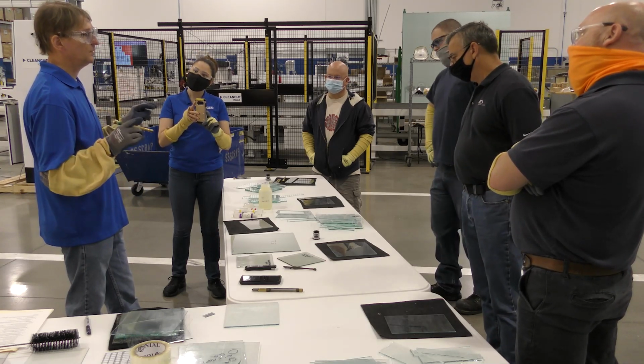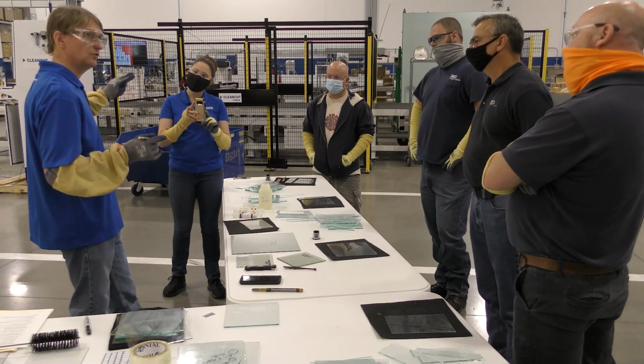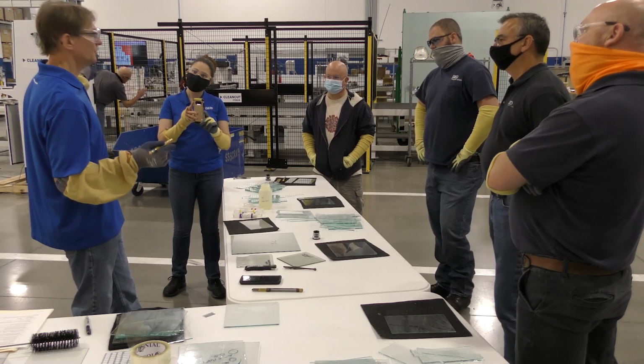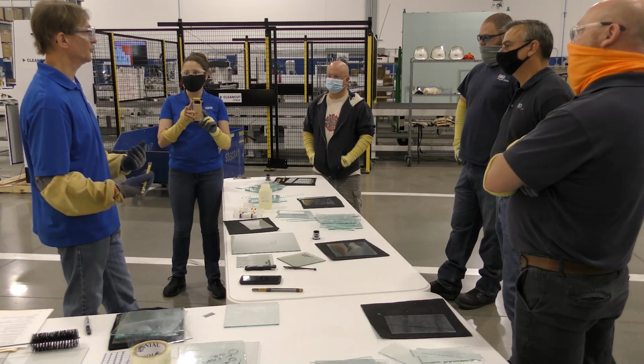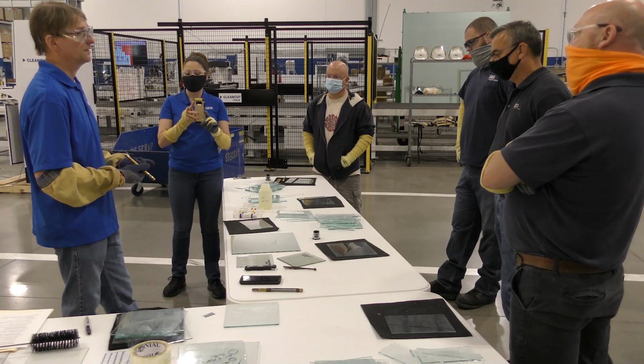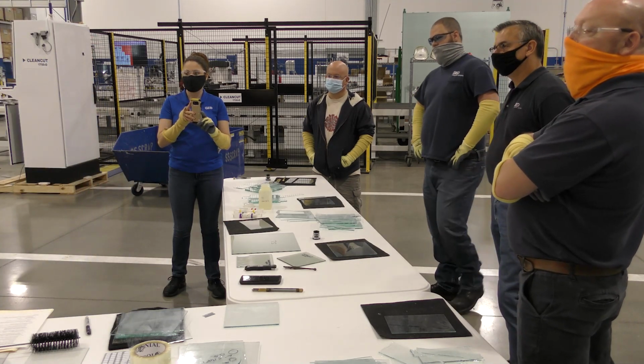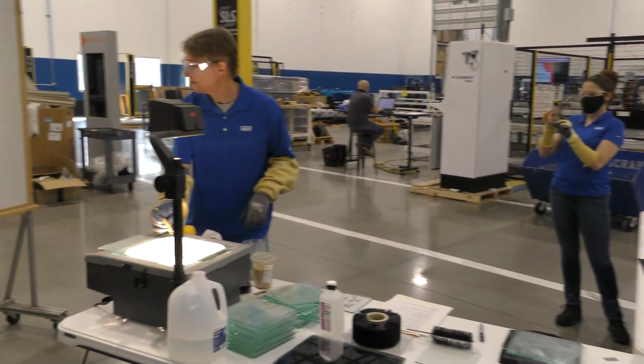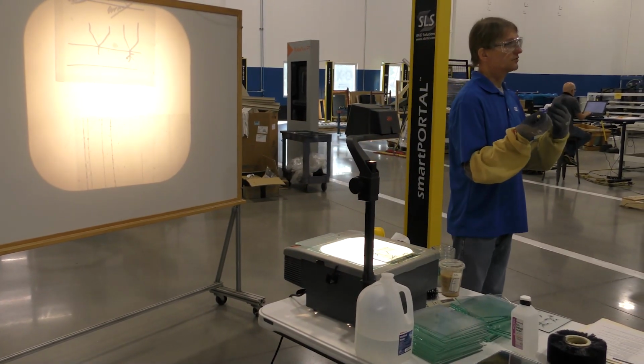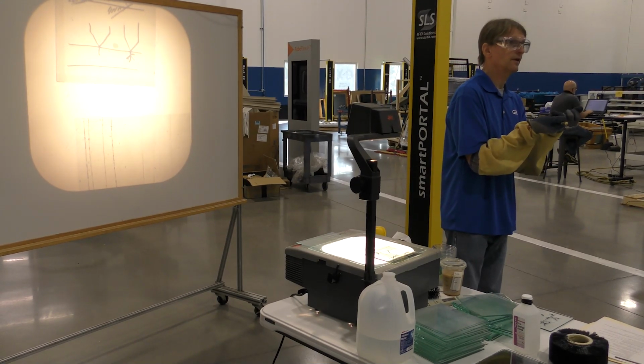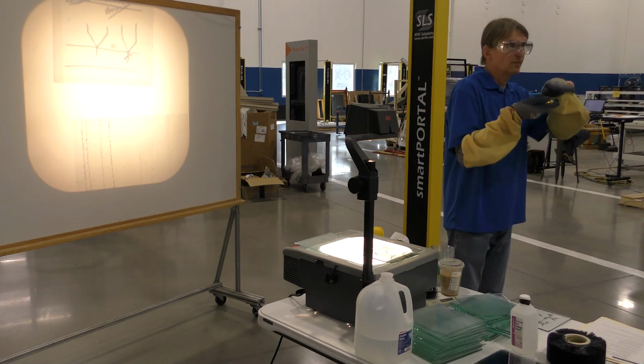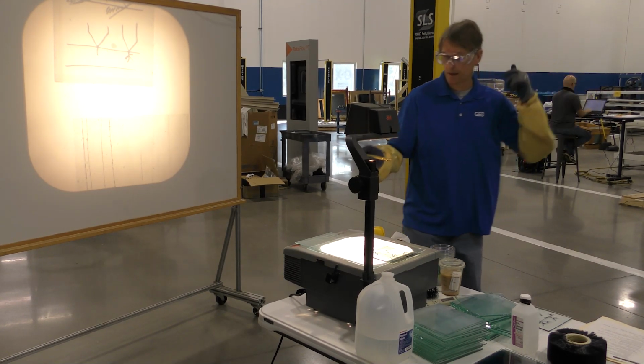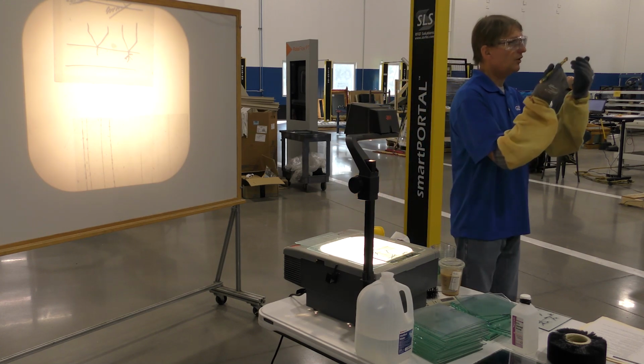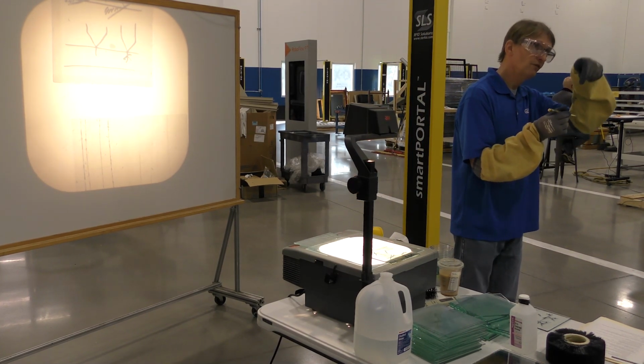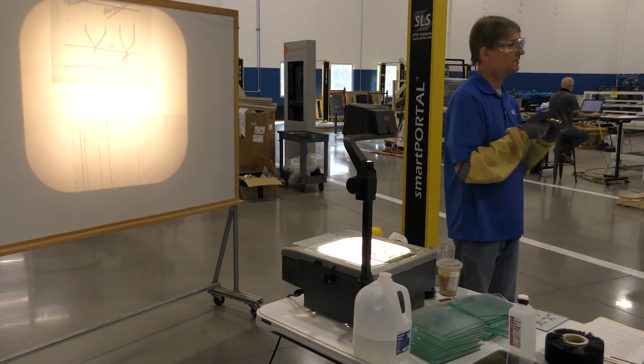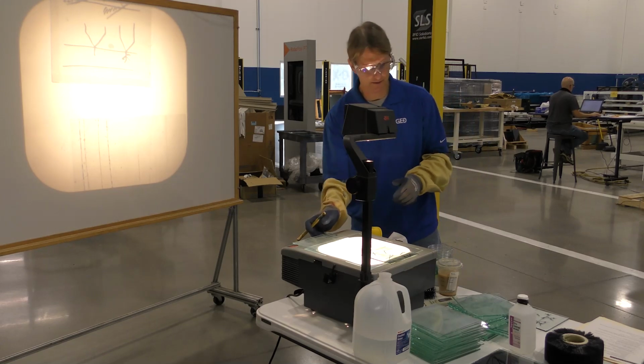And by healing, I mean if you store glass and you run it out on the breakout table, let it sit there for over lunch or overnight, and you come back in the morning, you will not be able to break that piece of glass. So the stresses that you see here, all of this hot cuts are stresses that were not able to be held into the glass. They release themselves between the compressive and the tension layer of the glass. They just pop. But ideally, you want to hold those stresses in the glass, in the fissure, such that when it comes out onto the breakout table, it breaks very cleanly and nicely.